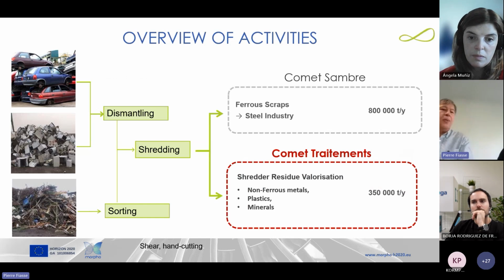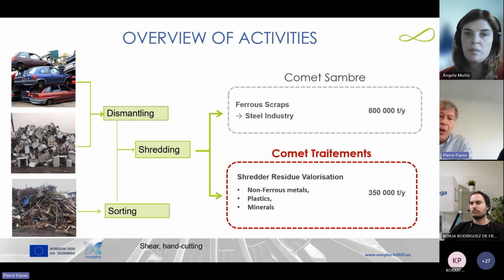So what do we do? We are dismantling first, sorting the waste, and then shredding. And the mother company, Comet Sambre, is with a magnetic separation, exploiting the ferrous scrap stream, and is active in the steel industry. Then after shredding, you have shredder residues, and that is the job of Comet Traitement to exploit. The aim of Comet Traitement is to focus on obtaining at the end secondary materials as close as possible to the virgin ones. So we recover non-ferrous metals, plastics, minerals. And it's very important to understand that the value of the material we can sell increases with the purification and sorting technique.